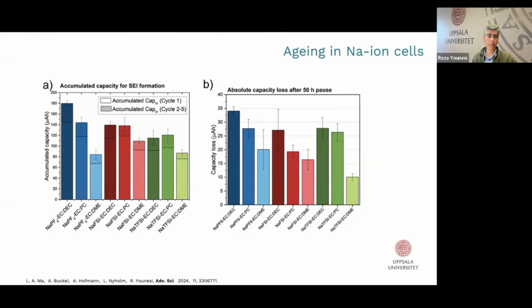So the outcome, as you see here, is that the least SEI dissolution was in electrolyte based on EC-DME in TFSI-based solution. On the left, you see that the majority of irreversible capacity is achieved during the first cycle, as expected. That's when the major part of SEI is formed during the first reduction.